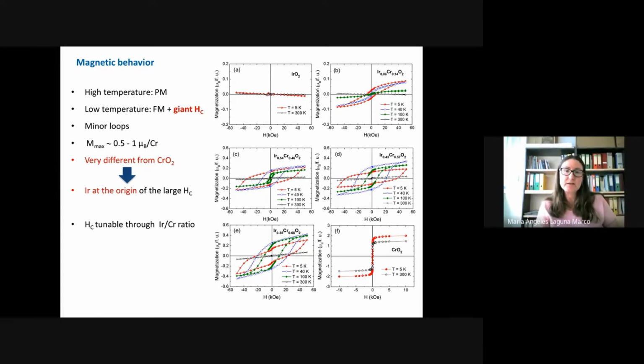This difference suggests that the presence of iridium may be responsible, at least partially, for the increase of the coercivity. And finally, the differences observed along the series allow us to conclude that it is possible to tune the magnetic coercivity by changing the iridium-chromium ratio.